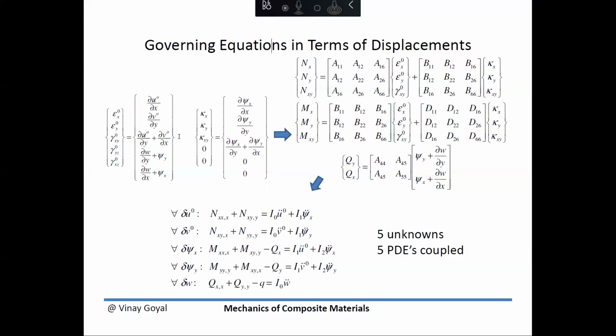So what we want to do then is solve for those five variables. And the way to do that is to plug these two into this constitutive law and then plug all that into these five equations. That way I can get everything in terms of u, v, w, psi_x and psi_y. As you see here, you get five unknowns and five partial differential equations that are highly coupled. And as discussed before, this is very cumbersome to solve using ideas from mathematics on how to solve partial differential equations in an exact way.